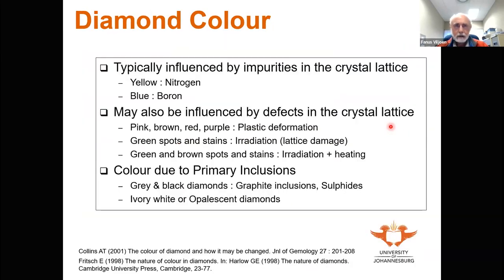Diamond color. Diamond color is typically influenced by impurities in the crystal lattice. And so, for example, if you have nitrogen structurally bonded into the crystal lattice, you would end up with a yellow color. In cases where you have nitrogen-free diamonds, but that contain boron, you end up with a marked blue color for the diamonds.